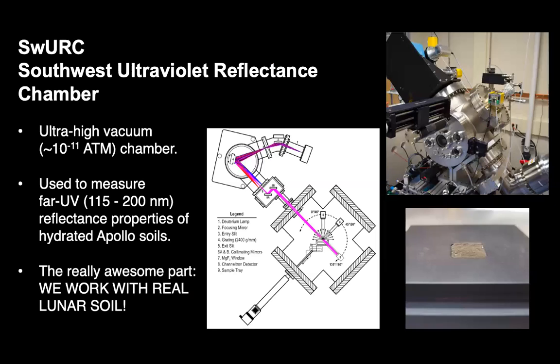So because we do not have a tremendous amount of extant data in the far ultraviolet, the group that I work with has built a chamber to do this kind of work and do it better than what was accomplished in that previous study I mentioned in the 70s. It's called the Southwest Ultraviolet Reflectance Chamber. It's an ultra-high vacuum chamber. It gets down to the mid 10 to the negative 8 torr, which is about 10 to the negative 11 ATM. It is used to measure in the far ultraviolet reflectance range, going from 115 to 200 nanometers.